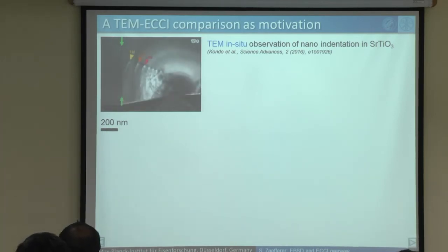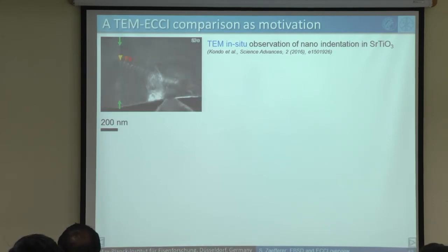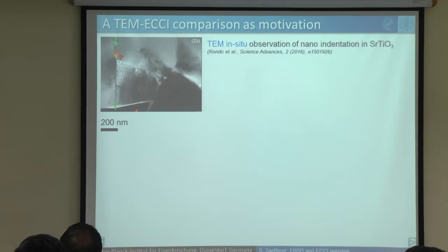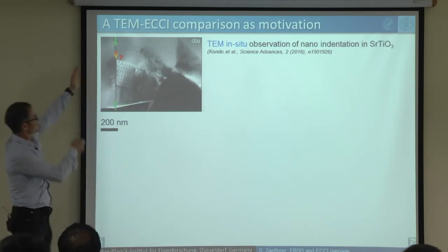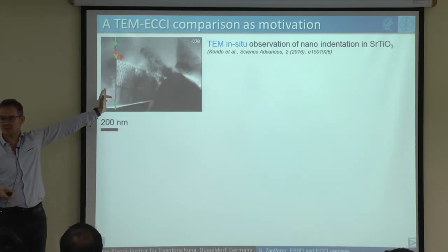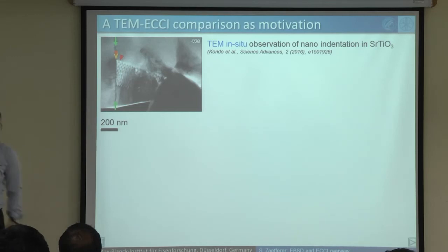And what you can see then is when you start indenting, you see dislocations piling up against this grain boundary, and after a while you see the dislocations get denser and denser while we are indenting here, and after a while you get a pop in, and then dislocations are forming everywhere, and you get a big pile up of dislocations here. Still no transmission into the neighboring grain. But this experiment is very nice and teaches us a lot of things, but it's probably one out of very few experiments which was successful.